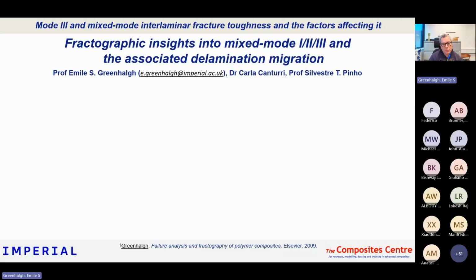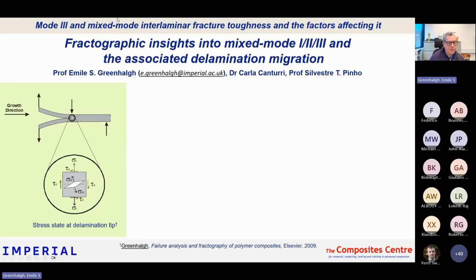I'm going to go through some fractographic observations related to mixed mode and mode 3 fracture and the associated process of delamination migration. So rather than going at this from the point of view of doing testing, we're focusing on trying to understand what the fracture processes involved are under those delamination conditions. Starting off with the mixed mode 1-2, if you look at the general stress state in that condition, you essentially have mode 1 tractions out of the plane of the laminate, and then these interlaminar shears that develop. And that results in an inclined crack at a particular angle, which is associated with that resolved stress.